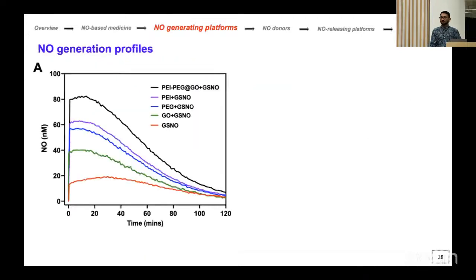And then coming to the nitric oxide generation profile. First of all, this is by using an electrochemical sensor, where we use a real-time release measurement to see if GSNO as an internal source in the bloodstream can produce NO over time. We just selected 10 micromolar, which is actually what the blood vessel produces every hour. We see that it also produces nitric oxide, but the amount is not therapeutically relevant.